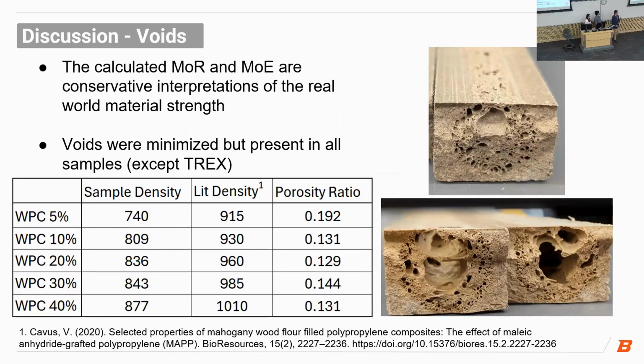And unfortunately, it's not possible for us to discuss our results without also discussing some of the challenges that we encountered. Predominantly, we found that there were substantial voids throughout many of our samples, which have impacted our results. Predominantly, the accuracy of the MOR and MOE is unknown, as it's not possible to quantify the exact impact that these voids had on those specific numbers. However, the hardness data was unimpacted, as the durometry testing was done on areas that were verified to be completely void-free.